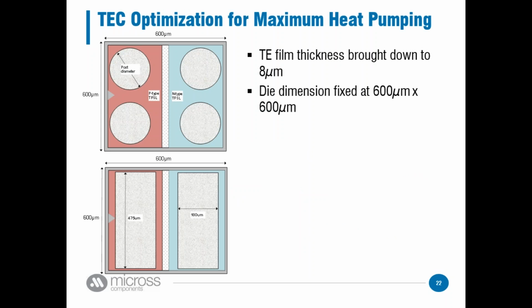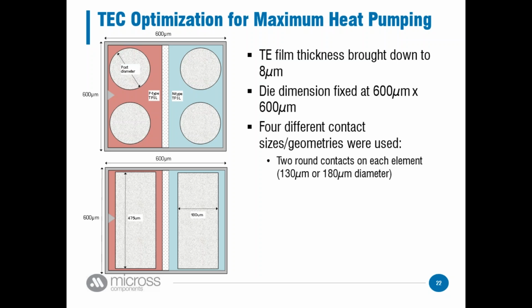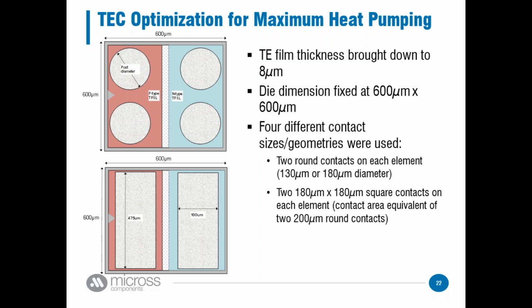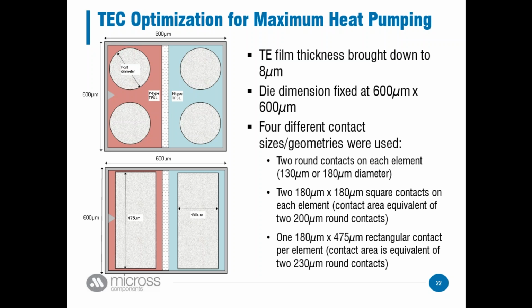So that's what we did. We brought the thickness down to 8 microns. We fixed our die dimensions at 600 micron by 600 microns, so we wouldn't have this problem with the drop in Q over A. And we looked at different types of geometries of contacts. We looked at basically having 2 round contacts on each N and P type. And we also looked at having these, instead of being round, be squares. But the big thing was to maximize packing fraction. We took a look at this guy right here, and I said, well, let's make our contacts as large as possible on the die. That's going to maximize our packing fraction. You can remember the F over L. And also with it being 8 microns here, that's going to minimize the thickness there.